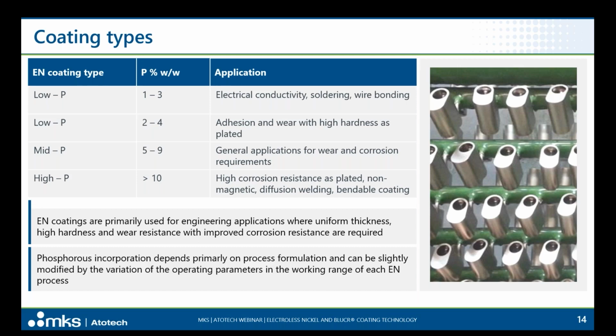So primarily all the electroless nickel coatings are used for engineering applications with uniform thickness, quite high hardness and wear resistance, and very good corrosion resistance. The phosphorus incorporation in the coating depends primarily on the process formulation, but by changing the bath parameters, we can change also a little bit of phosphorus content.